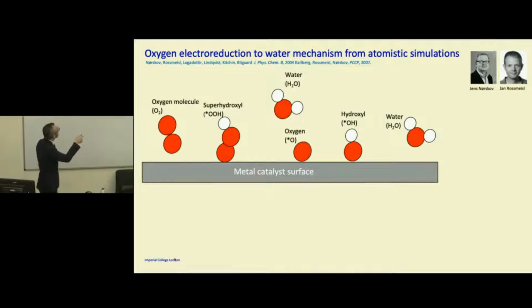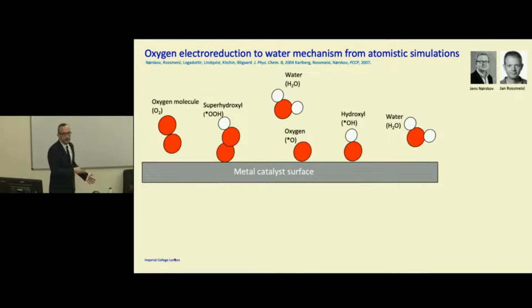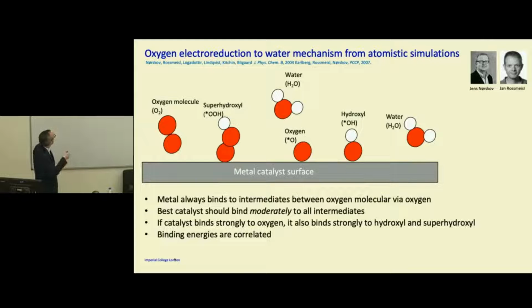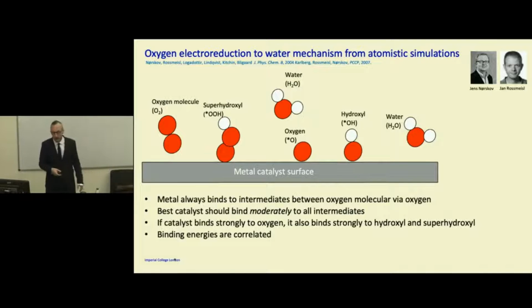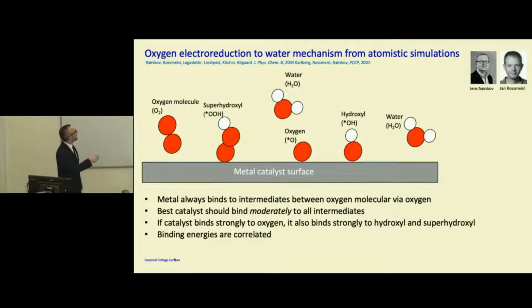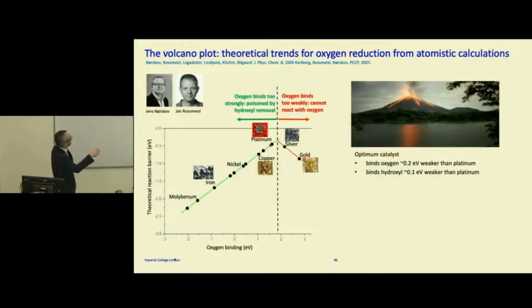The problem is that all of them bind via the oxygen atom, so they all bind in a very similar way. So this actually constrains the reaction somewhat. The binding energies of how strongly all these different species are bound are actually correlated to each other. So this constrains the reaction and constrains the efficiency of fuel cells. But the good thing is if you know the binding of one of these different reactive intermediates, you know the binding of the other intermediates. So then you get what's called a volcano plot. So this is where the title for my talk comes from.